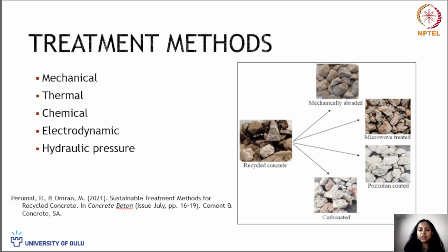So now we understand that this old mortar is creating issues for these concrete aggregates to be used in the production of new concrete materials. There are several treatment methods proposed in literature, like mechanical treatment, where you abrade this mortar layer and remove that old mortar, creating better aggregates or stones. And you can also do thermal treatment, wherein you apply high temperature, where the thermal expansion of the cement paste compared to the stone material is different, which creates a thermal shock, and the mortar layer cracks and falls off compared to the stone that stays intact at that temperature. It also helps in removing this old mortar from the surface.